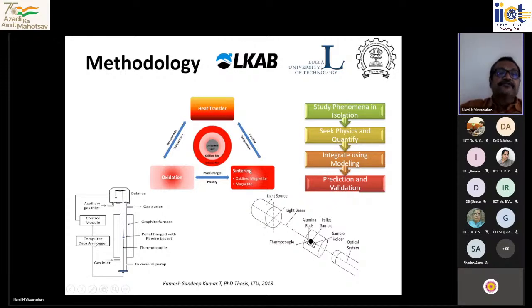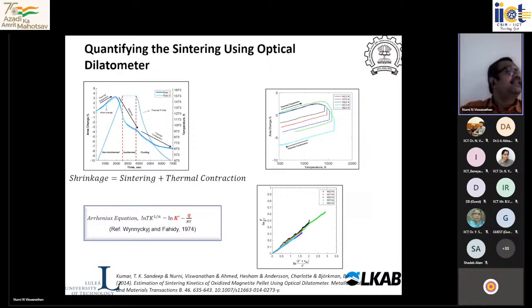The other way, of course, is well known: during oxidation, the sample absorbs oxygen, so its weight changes. We conducted experiments at two scales: one at the powder scale, and the other at the pellet scale. Once you have looked at the phenomena in isolation, you have to make sure that when you do oxidation, you should not sinter, so you do it at a lower temperature. And when you do sintering, you make sure either that the atmosphere is such that it doesn't oxidize, or that you oxidize first and then do the sintering. So one has to look at things in a systematic fashion, and that way we conducted these experiments very carefully.